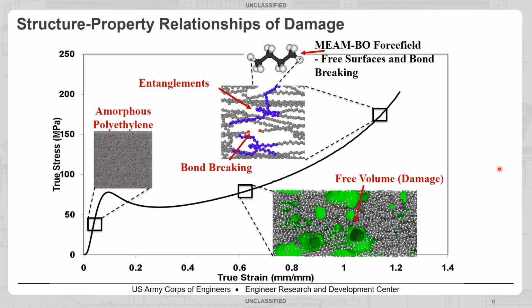So here we have just a generic curve for a polymer. Up here we look at amorphous polyethylene, and as that's deformed, we see the accumulation of free volume or damage within the system. Eventually that leads to disentanglements and bond breaking within the system. All of these are related to each other in complex fashion. And we want to use this force field called the MEAM or modified embedded atom method with bond order. And this allows us to have a high accuracy look at free surface formation and bond breaking and bond forming during deformation. So we will take a closer look at that in a second.